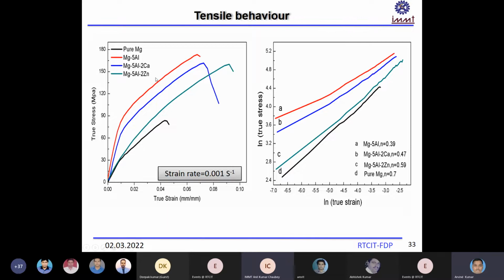But adding zinc to 2%, you are getting a better ductility, and you can see that the strength is also higher than calcium. So that's why the calcium is not effective in this case. Zinc is effective, but 2% zinc is not much more effective. So we have to go to a higher percentage of zinc if we need more ductility, but strength is expected to go down.